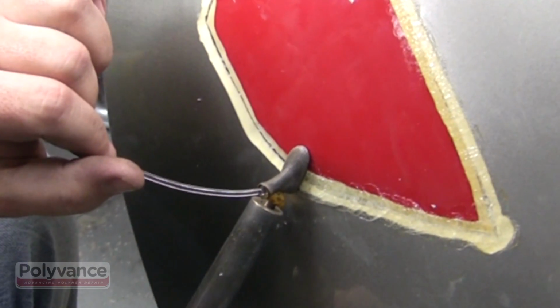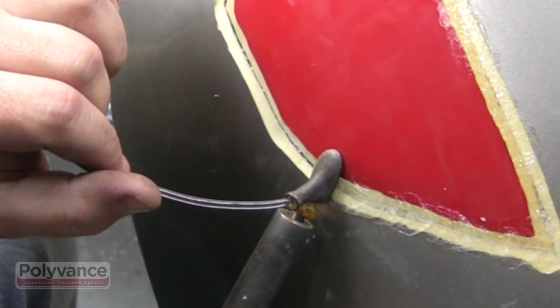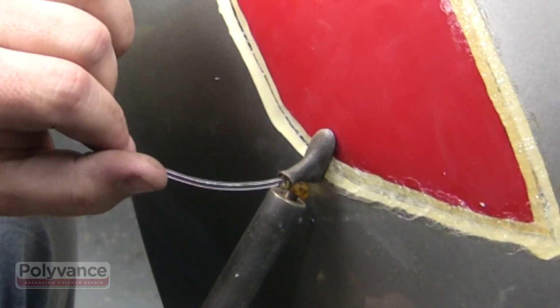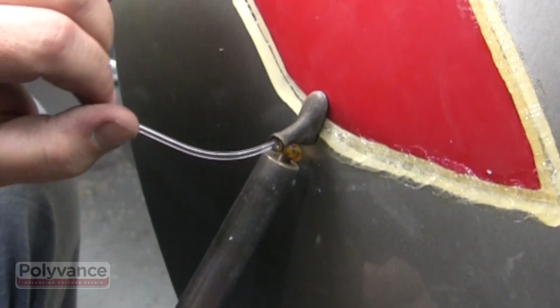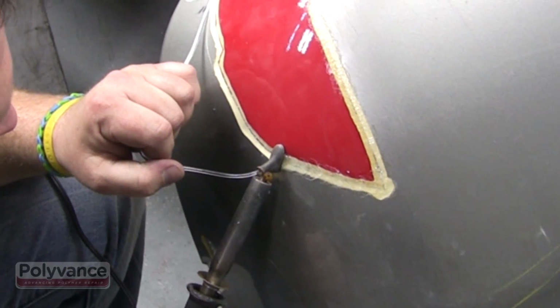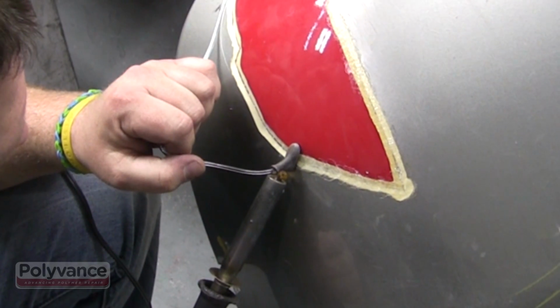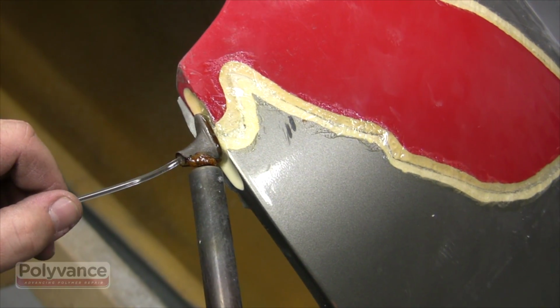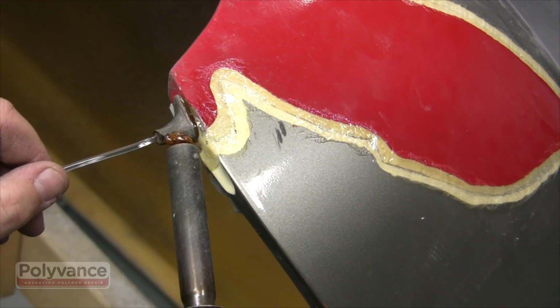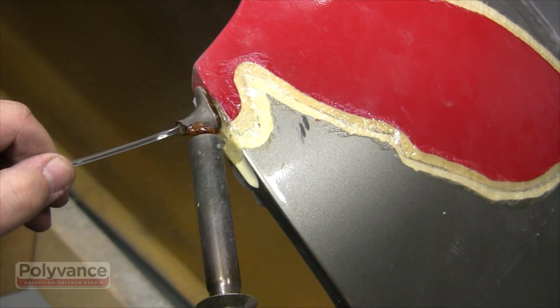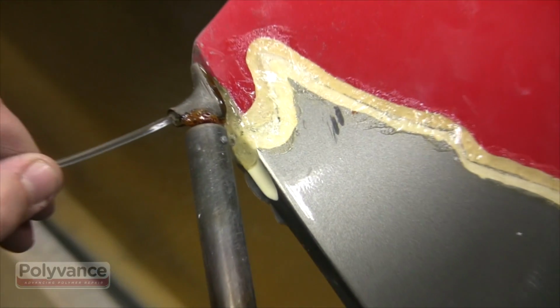Because the fender is made of thermoset urethane, it is not meltable. So when we repair urethane with the airless plastic welder, we are not actually welding the plastic. Instead, the repair is more like a braze or a hot melt glue. The urethane welding rod has very good adhesion to the plastic and makes a very strong repair.